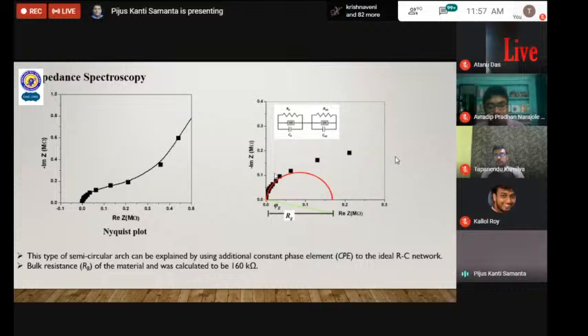To understand the various contributions like grains, grain boundaries, and interface into the impedance spectrum, we use the Nyquist plot where we have plotted the real part of Z and negative imaginary part of Z. We get a pattern sort of like this. So this pattern can be divided into two parts. One is this semicircular arc, and this is a larger arc. So the first part is responsible for the bulk contribution, and the second part is for grain boundary. And we see that this arc is quite large. This indicates that the grain boundary has a large contribution in the electrical conductivity of this material.